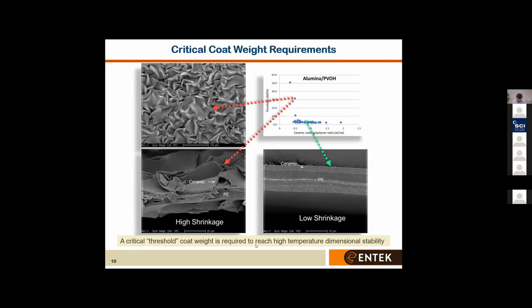Now, we've defined a critical threshold whereby the ceramic coat weight must be a minimum of 0.45 of the polymer mass within the body of the separator. Below this threshold, as you can see from the chart and the upper left SEM, the thermal shrinkage of the base PE causes buckling of the composite at elevated temperatures. Above this threshold, so above that 0.45, the coating locks in the structural integrity of the separator composite such that at 180 degrees C, well above the melting point of polyethylene, we see less than 3% shrinkage after an hour at 180 degrees C. So that truly is remarkably strong thermal robustness.